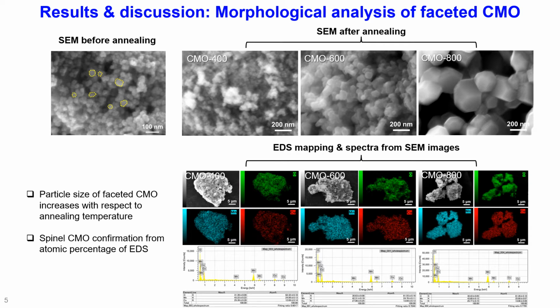Here I have to mention that the CMO produced from 400, 600 and 800 degrees Celsius post annealing was named as CMO 400, CMO 600 and CMO 800 respectively. Here we can see that CMO 400 shows so much aggregation with very small particles. CMO 600 shows some facets. CMO 800 shows the clear faceted morphology due to the bigger particles.